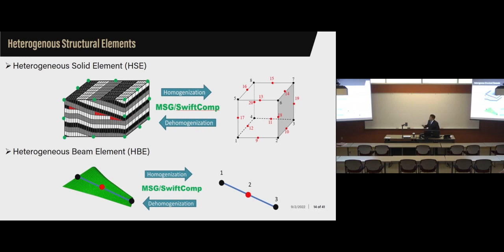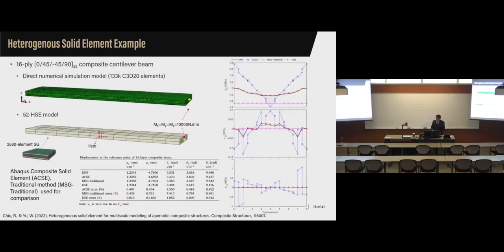Then basically, even at the homogeneous level, the displacement and the stress and strain could be not homogeneous. It could be heterogeneous. For 20 nodes, you're basically up to a quadratic distribution for the stress and the strains. And we did a few examples, and one of the papers is already published, that is the heterogeneous solid element. And we compared with the Abaqus composite solid element and also the traditional multiscale modeling, still using MSG, but homogenized to a point in the global analysis.